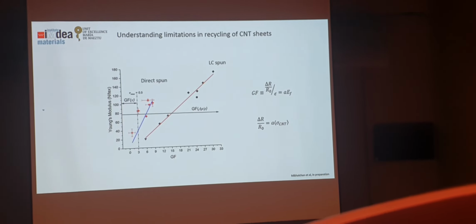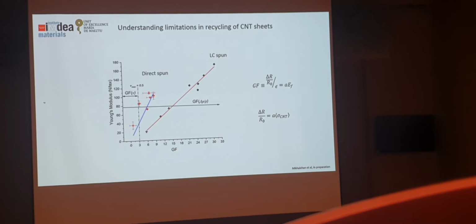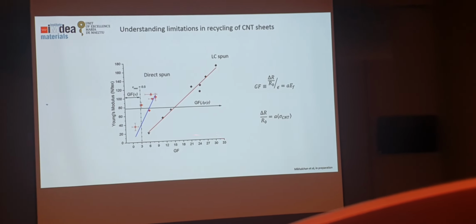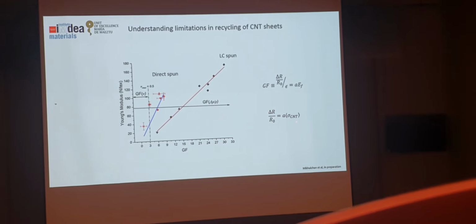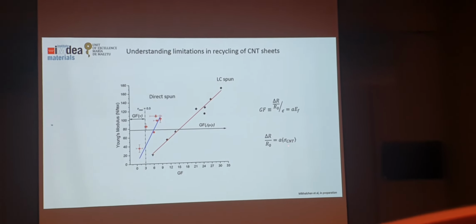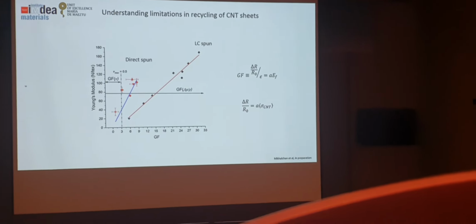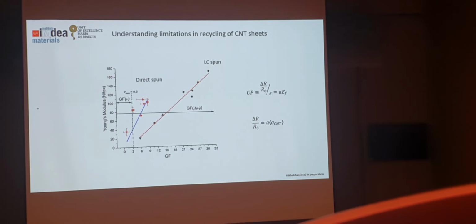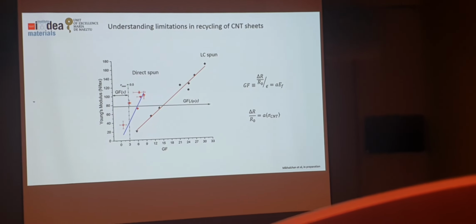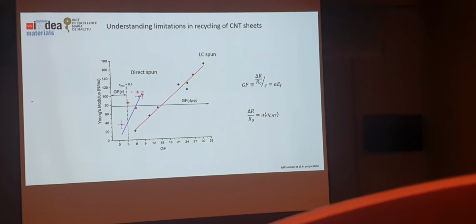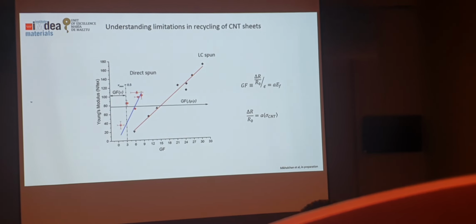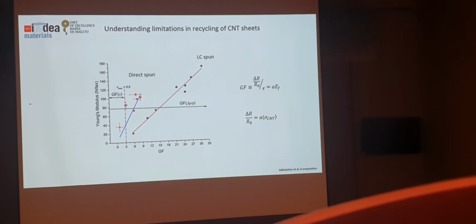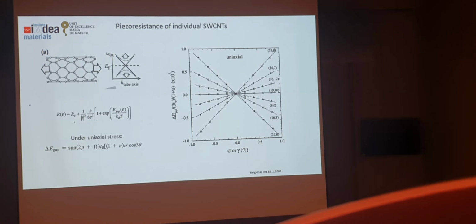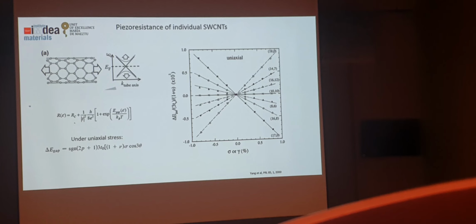So the more you can transfer stress to it, the more the change in resistance. So that's more or less expected. I mean, what we're saying is the change in resistance is proportional to the stress transfer to the CNTs, right? So the piezoresistance is coming from the deformation of the CNTs, and that's important. So you don't see that when you make low volume fraction filler composites. And what we've been trying to work out is, well, where does that come from?